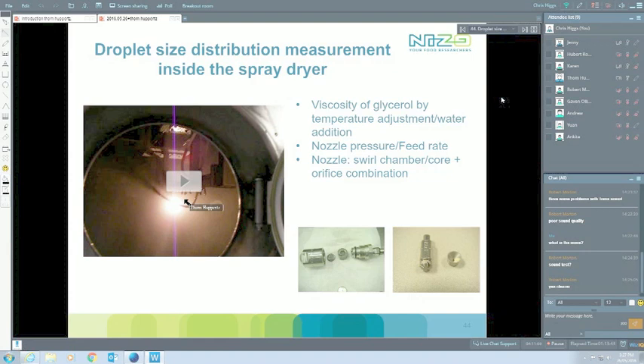So we needed to think of something else and say, okay, if we take glycerol, a very well characterized sample of course, then we can use glycerol-water mixtures. They're independent of shear from a viscosity perspective, so we can get them at the right viscosity by simply measuring at room temperature. We know the temperature dependence there, and we can make a very nice model system that we can use to look at atomization, to see what's going to happen when we change nozzles, pressures, feed rates, anything like that. And really select, okay, if we're going to have a sample with a certain viscosity, what is going to be our most optimal